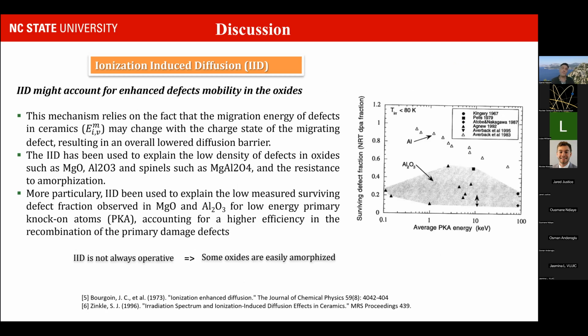In the literature, there's very little information on radiation damage in magnetite or chromium oxides or hematite, all those major scales that build in a reactor. But there is some information on specific oxides, and we were able to see a couple of models that discuss enhanced diffusion of defects in oxides. One of them is ionization-induced diffusion, and that process relies on the fact that the migration energy of the defects in ceramics, such as oxides, may change with the charge state of that migrating defect. And usually it lowers the diffusion barrier, making it more mobile. That has been used to explain the amorphization resistance of some oxides, but it doesn't seem to be active in all oxides or to the same extent, because some other oxides amorphize extremely readily.